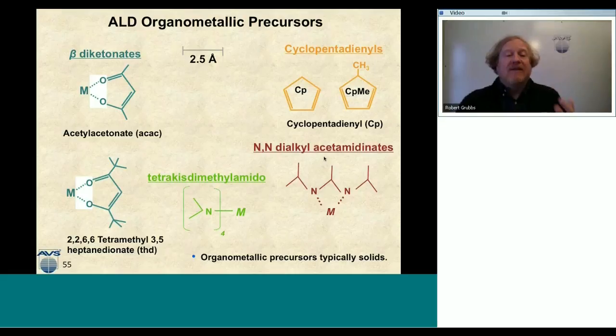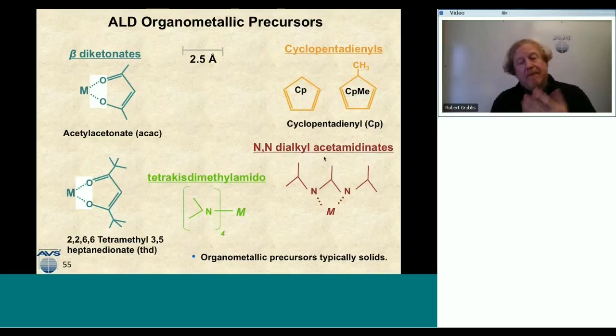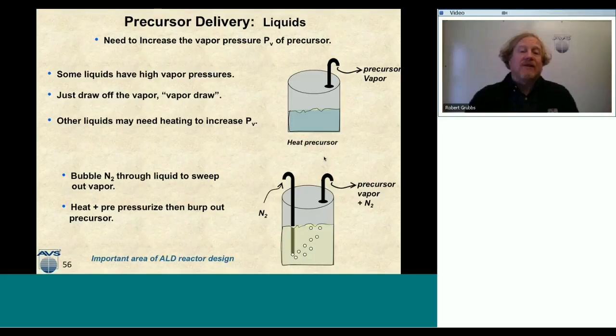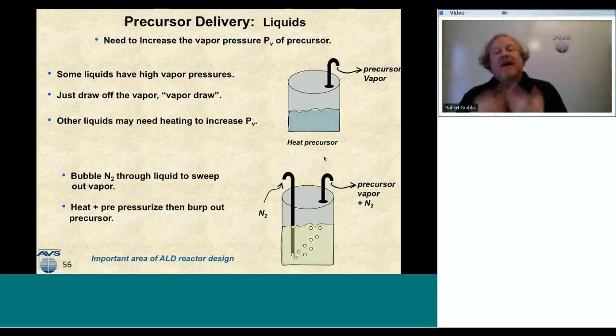Now, I mentioned that precursors can be gases, liquids, and solids. Ideally, they're gases. Second ideal would be high vapor pressure liquids. And what you don't want is to work with solid precursors. But these organometallic precursors are typically solids, so you need to heat them up in order to get the vapor pressure up. When we talk about liquids, we know that we can deliver liquids in a few different ways. We need to increase the vapor pressure of the precursor in order to get enough of that vapor up into the chemical reactor to coat our parts.